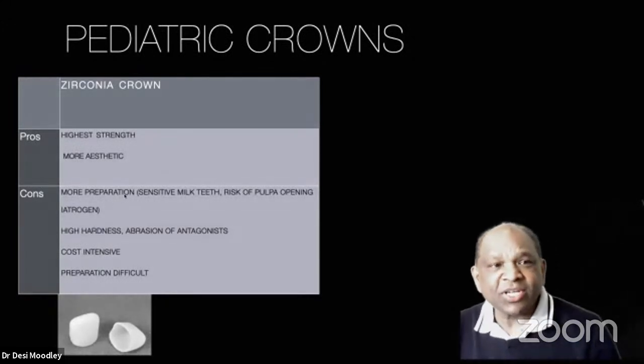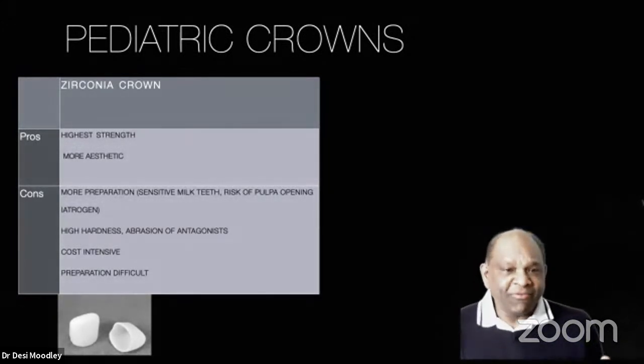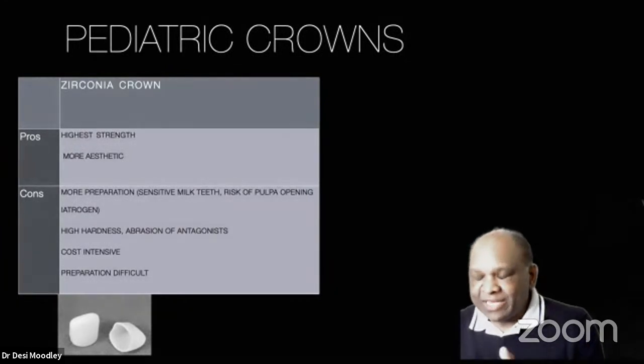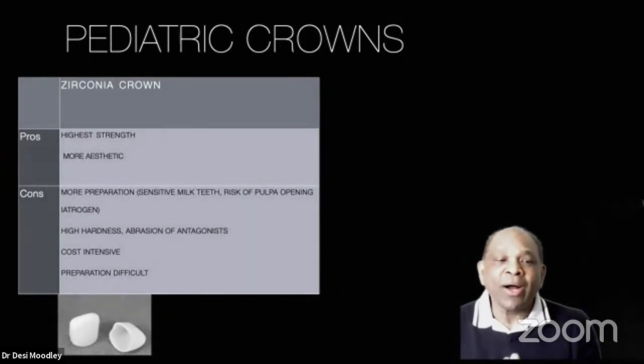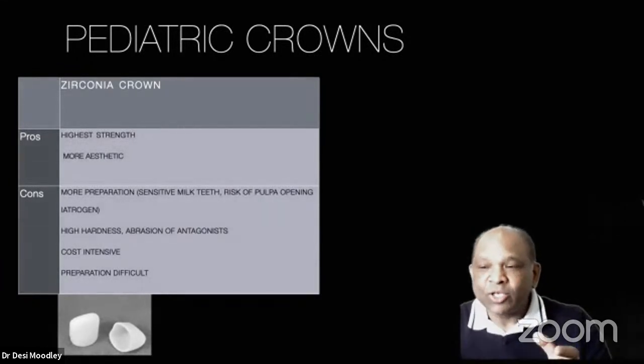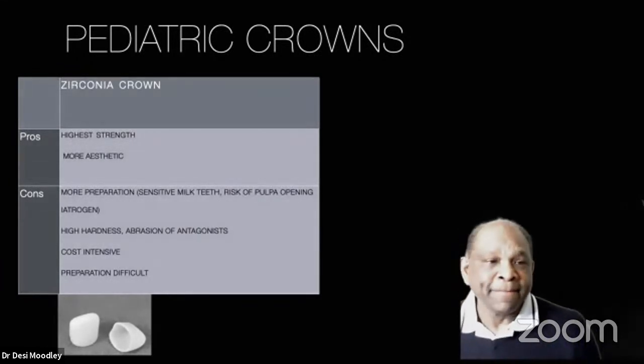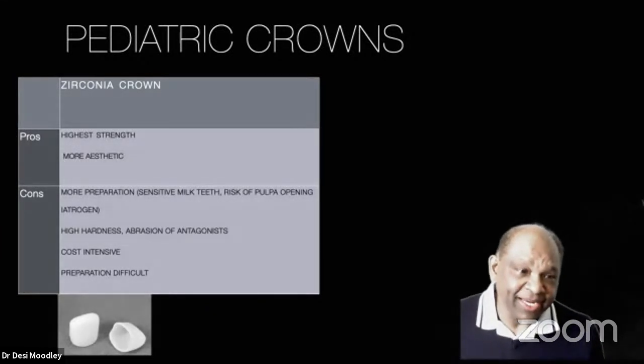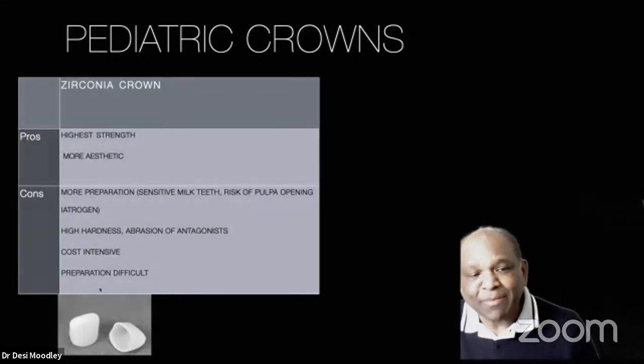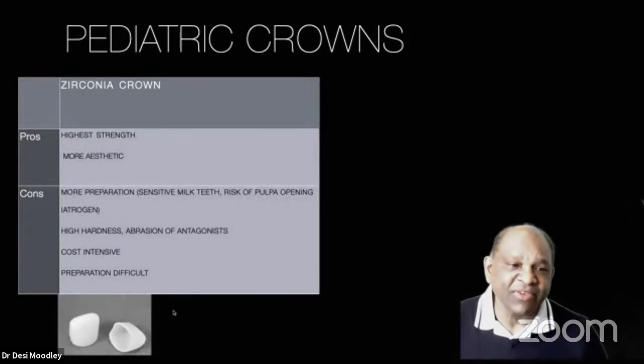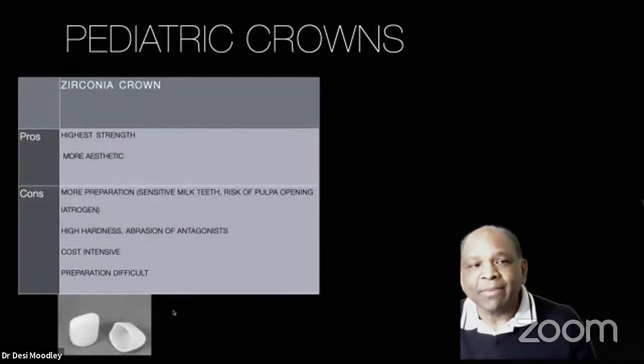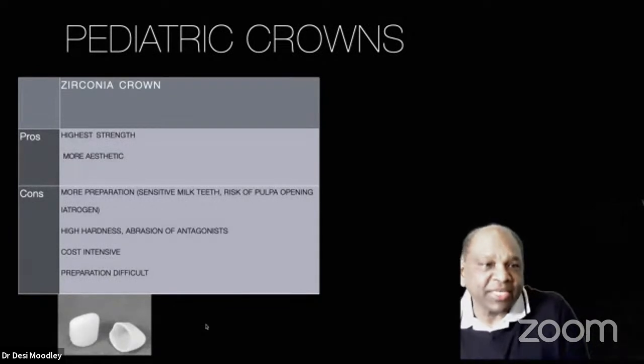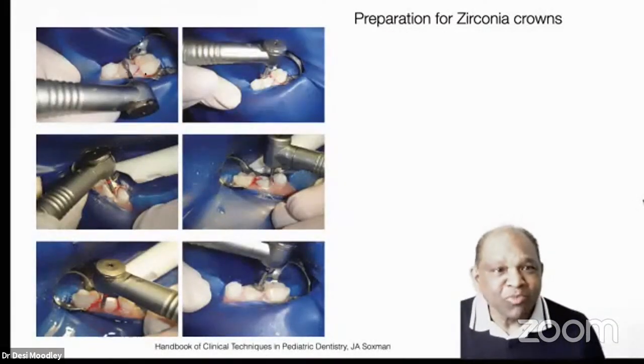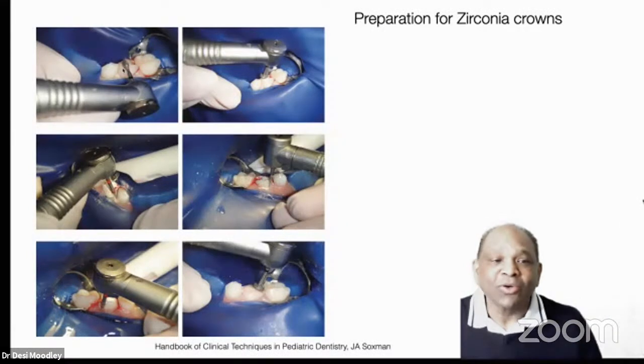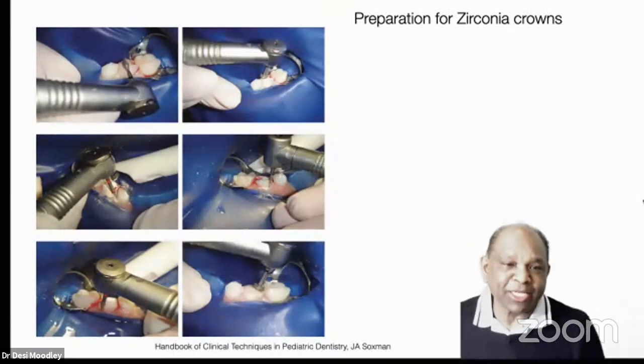The disadvantages of these zirconia crowns are that, firstly, the preparation itself is extremely difficult. You are required to remove a lot of tooth structure. And of course, the material is very hard. It's quite expensive, and the preparation itself is not easy. So we'll look at a little bit about the zirconia crowns and the preparation itself. We need to remove at least 1.5 to 2 millimeters occlusally, which is quite a bit, and there's a chance of iatrogenic damage or pulpal exposure.